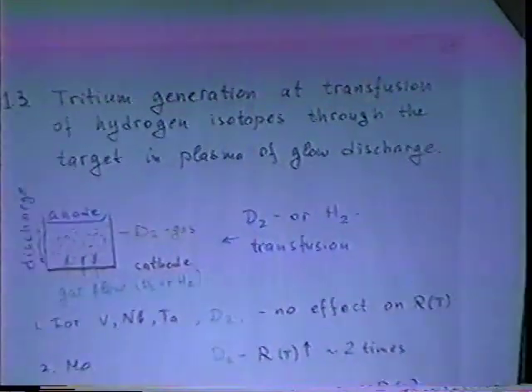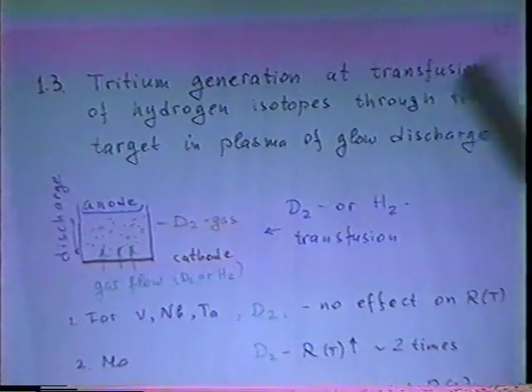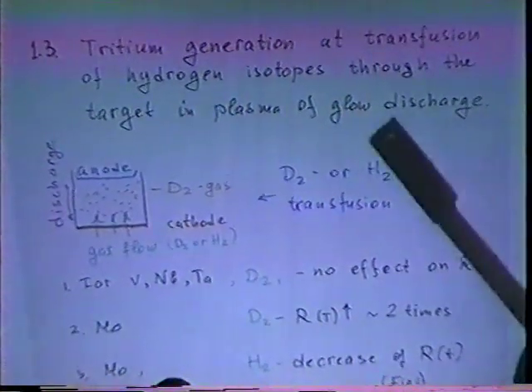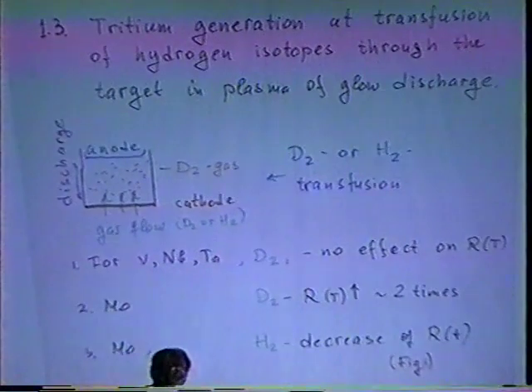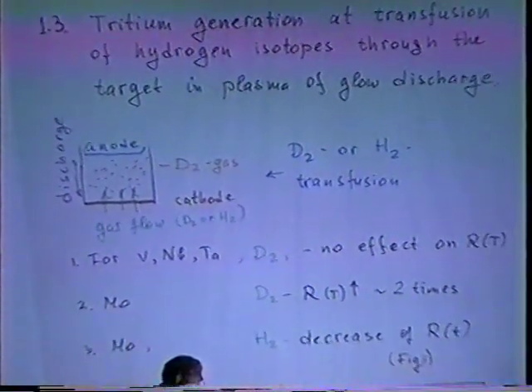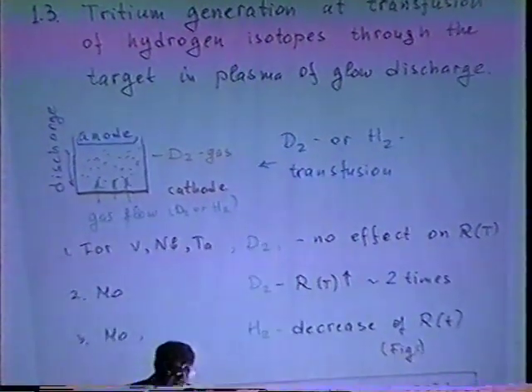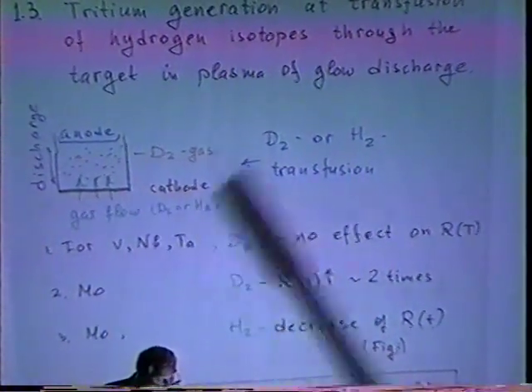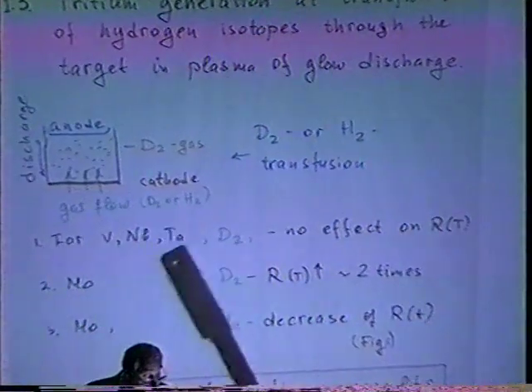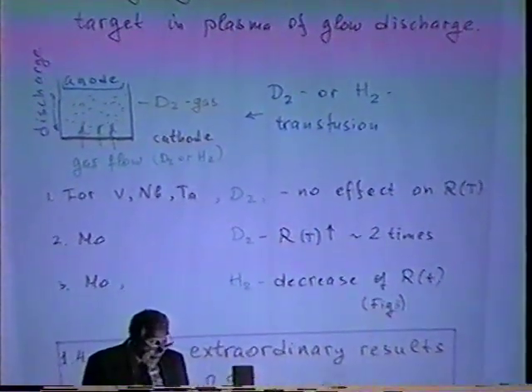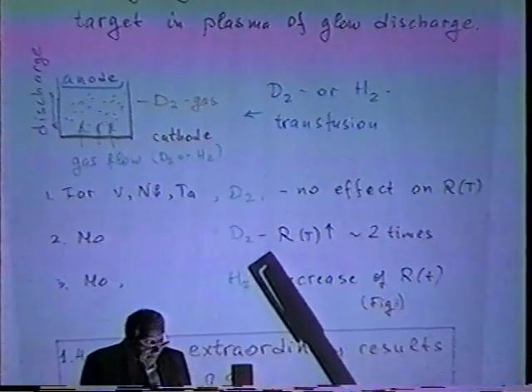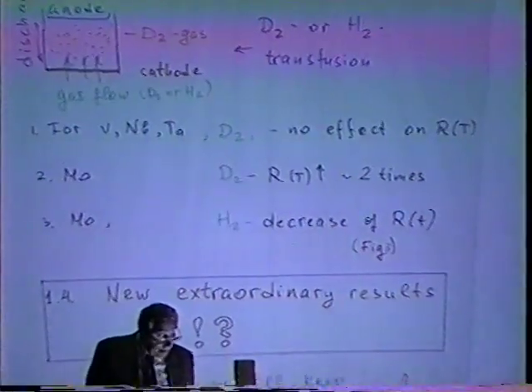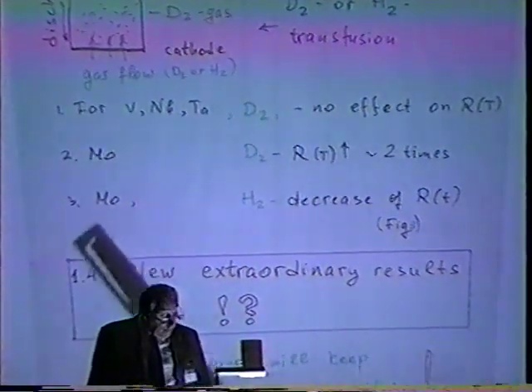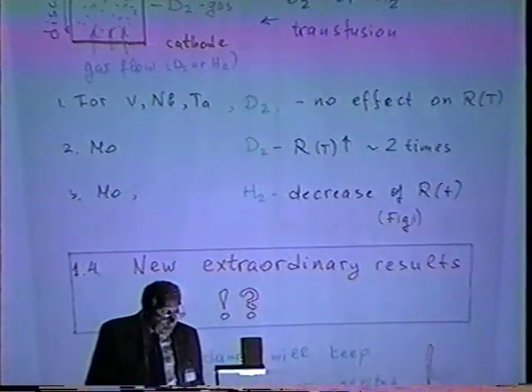The last paper presented to this conference, submitted, is on tritium generation and transfusion of hydrogen isotopes through the target in plasma of glow discharge. So, in addition to their usual experimental procedure, they use the transfusion of gas. And the gas can be deuterium or hydrogen. For some of the cathode materials with deuterium, they didn't observe any effect. For molybdenum, they observed a not very high, but about 2 times larger effect. And for molybdenum with hydrogen transfusion, they observed a rather visible decrease of the effect.